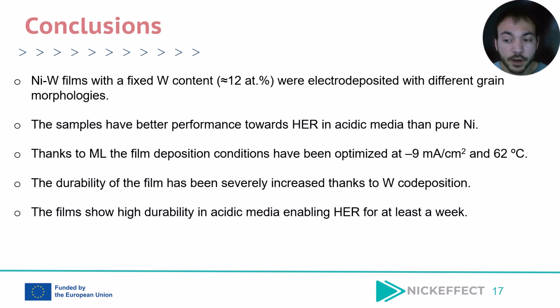To conclude, we were able to deposit nickel tungsten films with a fixed tungsten content around 12 atomic percent, also obtaining different grain morphologies by changing the current density or the temperature. The samples have a better performance towards hydrogen evolution reaction in acidic media than pure nickel. Thanks to the machine learning, the film deposition conditions have been optimized to minus 9 milliamperes per centimeter square and 62 degrees. The durability of the films has been severely increased thanks to the tungsten co-deposition, and finally the films show high durability in acidic media, enabling hydrogen evolution reaction for at least a week.